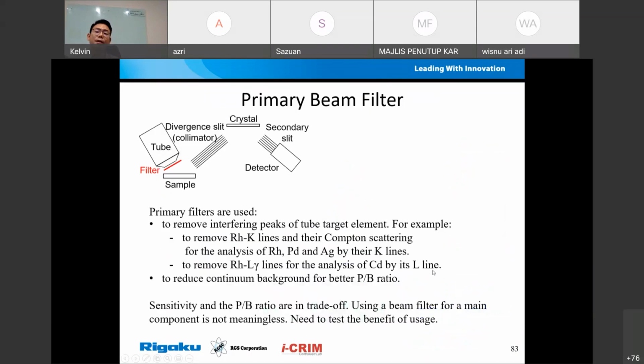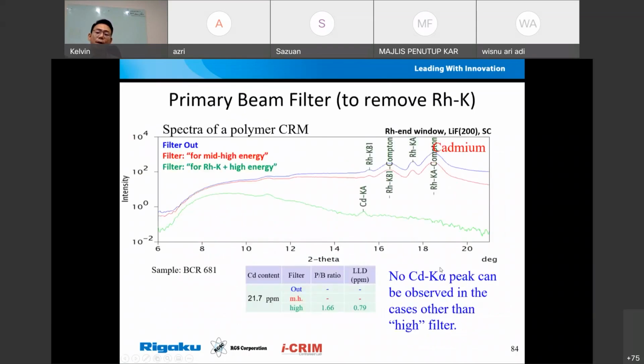Another one is the primary filter. As I mentioned to you just now, the primary filter itself can remove the background. In the system, it automatically determines which filter to use. When you want to measure cadmium, the system will automatically pick this filter. Then you can see that the cadmium peak is very obvious, compared with no filter at all, where you cannot see the cadmium peak.